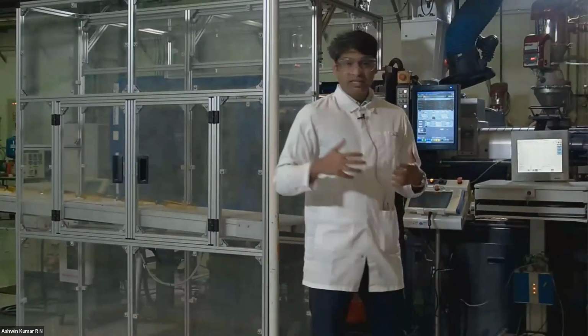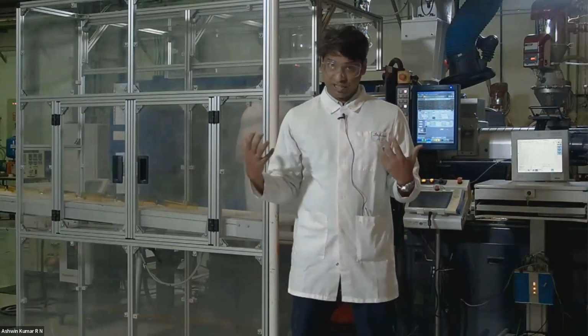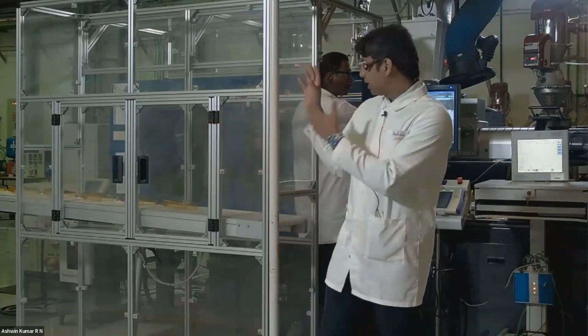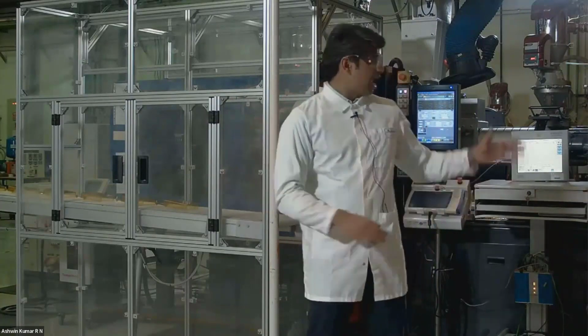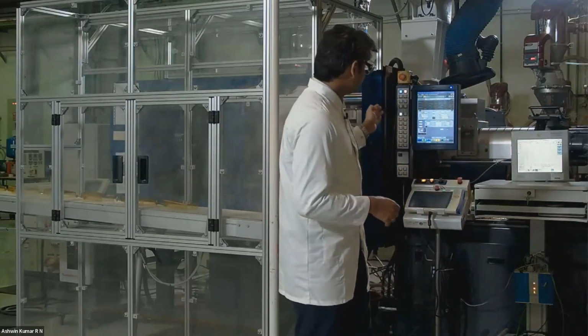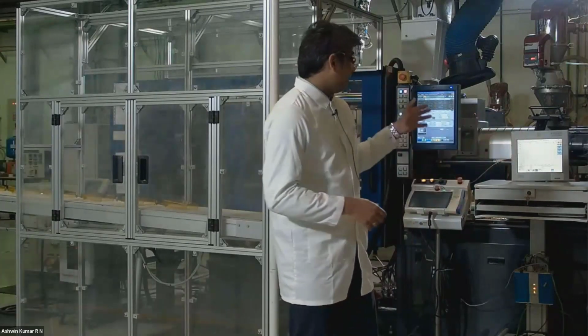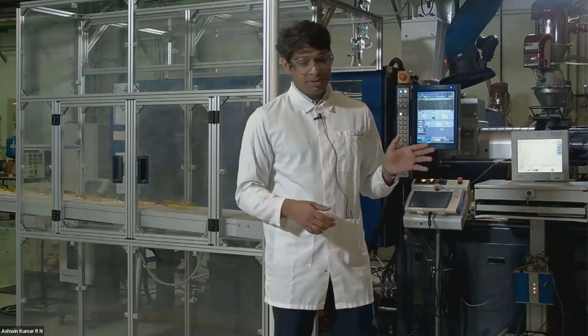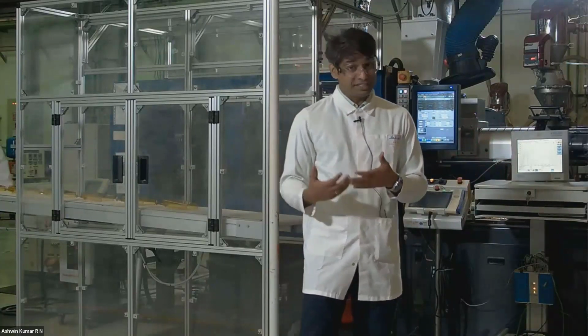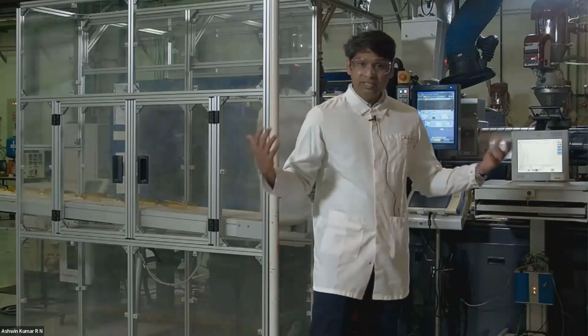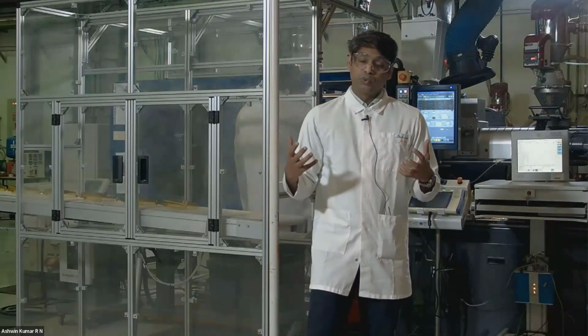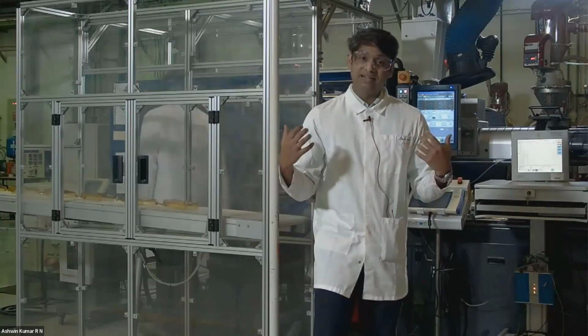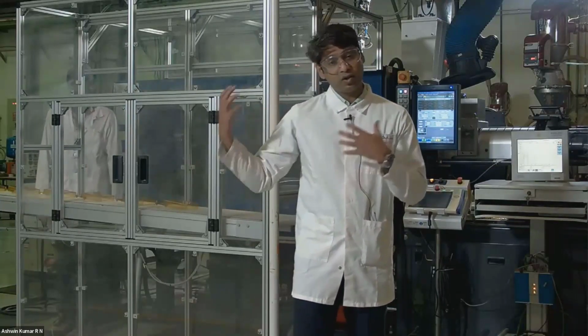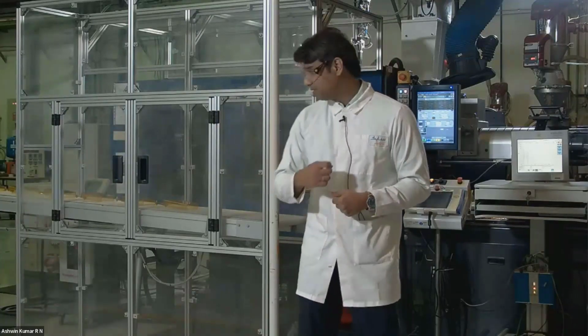Before I start off with understanding the process, I just want to introduce the molding infrastructure here. What I have here is a Sumitomo-make all-electric, high-speed, high-pressure machine. On the clamping side, it can deliver 130 tons. And on the injection side, it's a 36-diameter screw with about 140 grams of shot weight. It can achieve screw speeds of 360 mm per second, and the pressures can go up to 290 megapascals on this unit. Supporting this molding machine, there are a lot of auxiliaries which are equally important to get a uniform, streamlined, robust molding process. So I'll quickly show you the auxiliaries which go into molding this sample here.